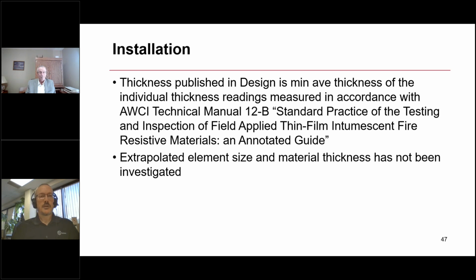So there it talks about thickness, how to measure the thickness, and determine the right thickness on the column or beam, the structural member in the field. When we test columns and beams in the lab, maybe on a 9-foot column or a 13-foot long beam, we take maybe 80 or 100 readings here in the lab to ensure that the coating thickness is uniform, so we know what we're testing. But do you have to measure it that many times in the field?